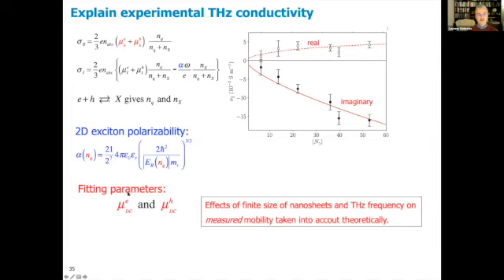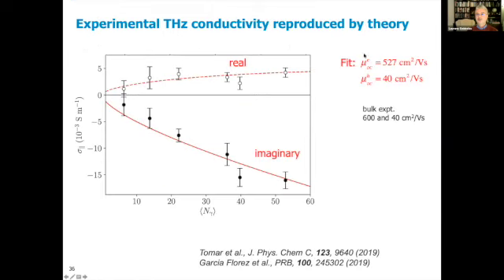Now, the only fitting parameters we had are the mobility of the charges within a nanosheet, and that we took as adjustable parameters to get these theoretical curves. We found that the DC mobility of electrons and holes had to be 527 centimeters squared per volt second and 40 centimeters squared per volt second, and these fitted values are close to the bulk values. They can deviate a little bit because the band structure of a 2D material deviates from the band structure of a 3D material, so the effective mass can be a little bit different.